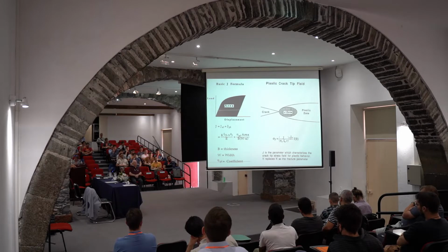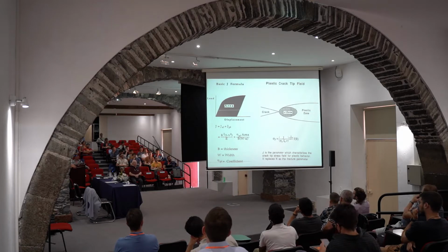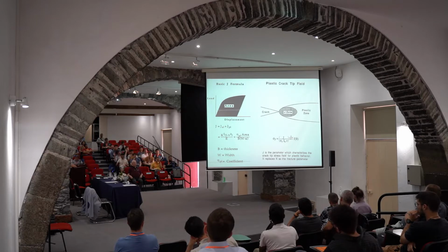One of the first attempts, and later on used quite often, by Landes and Begley, is to measure the area on the diagram of displacement and to divide J into elastic and plastic part, and then to express the elastic part through the K factor and to correlate the plastic part with this area. Now this is the second important thing about J integral, and the third one is that it is a parameter characterizing plastic crack tip fields. Those are famous, as we call them, HRR fields, that is due to Hutchinson, Rice, and Rosengren.